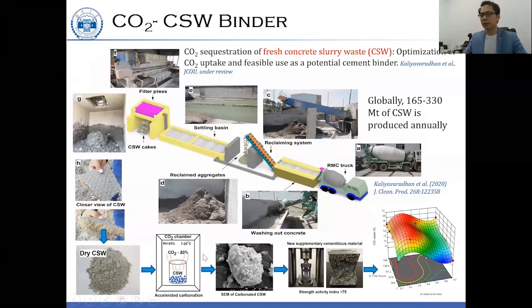So we ran it under the dry carbonation process in the CO2 chamber at RH of 65%, 20 degrees, and CO2 concentration of 20%.